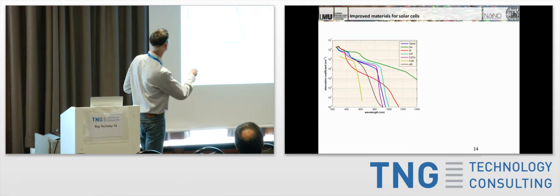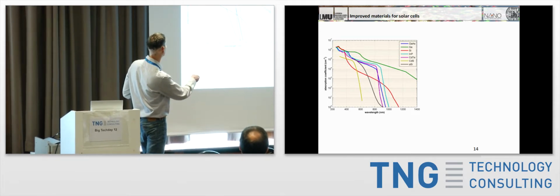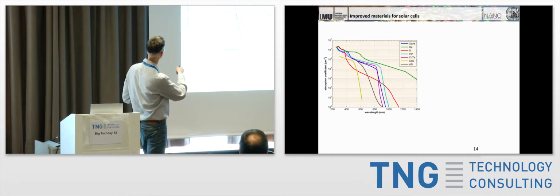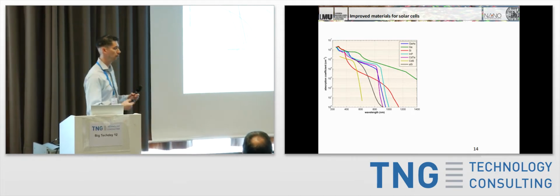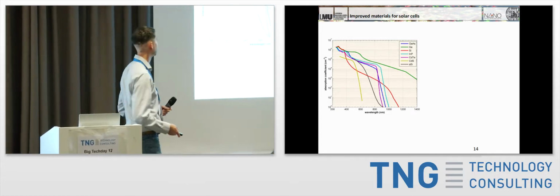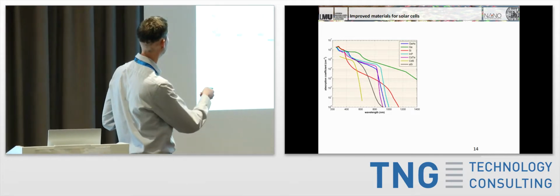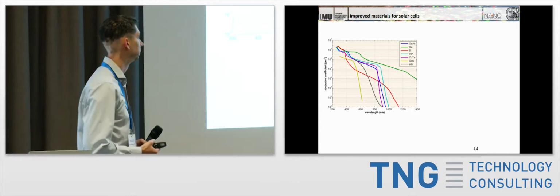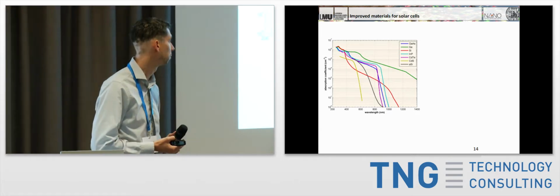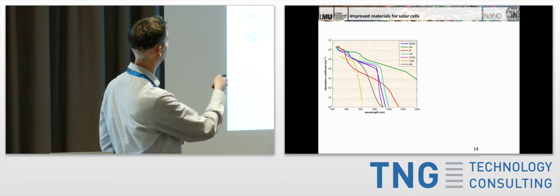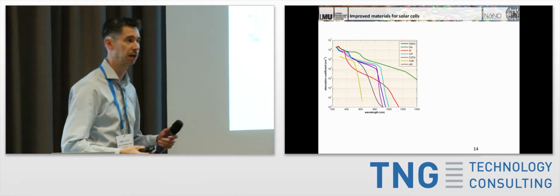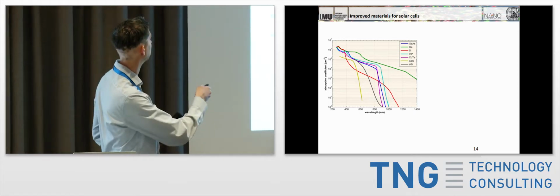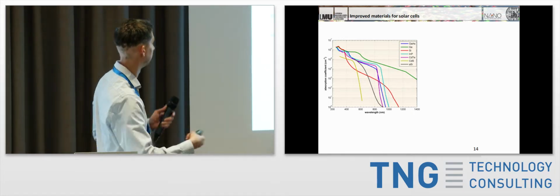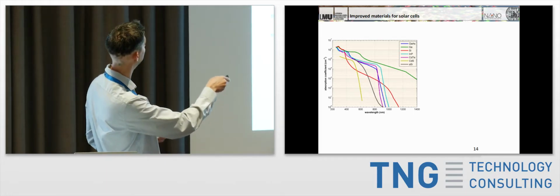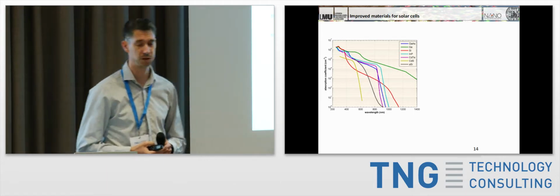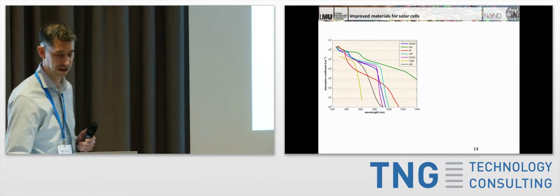Okay, so let's look at some of these materials that we have out there. So crystalline silicon is this red one here. It's about 1100 nanometers, something that goes out here. And what we're showing here is the absorption coefficient, so how thick a material needs to be to actually absorb the light. And you can see that there are a lot of materials that have different band gaps, so they're shifted possibly further to the blue part, to the visible part of the spectrum. But you can see quite quickly that they have absorption coefficients that are much, much larger than silicon. That means they absorb much, much more intensity. And it's actually done in a logarithmic plot, so essentially one of these is a factor of 10. And so you can see quite easily that soon these materials absorb 100 times as much light as silicon does.